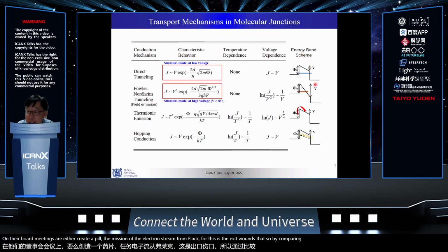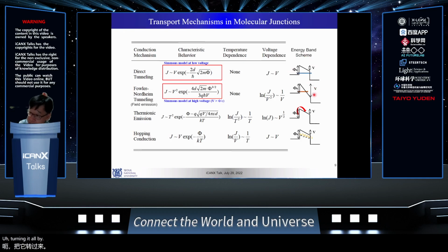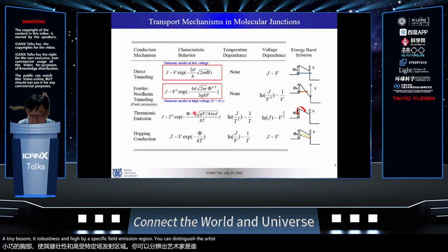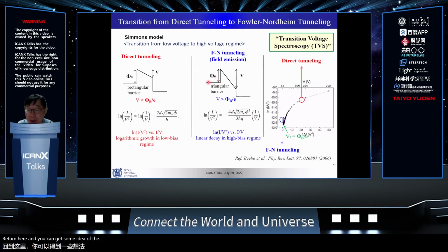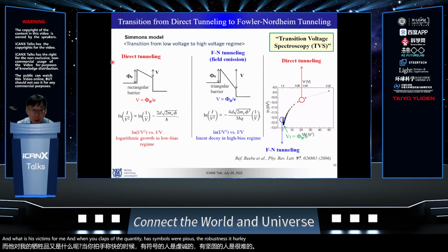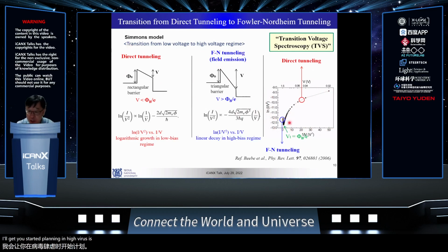So by comparing the tunneling regime at low bias and the field emission regime at high bias, you can distinguish this relationship, and you can get some idea of what the barrier height is. So this is so-called transition voltage spectroscopy. When you plot a certain quantity as inverse of bias, low bias is direct tunneling, and high bias is field emission tunneling, and you change the two regimes. Those regimes change when the bias is roughly equal to the barrier height. So it gives the idea of the barrier height, meaning the energy level of the orbital of the molecule.